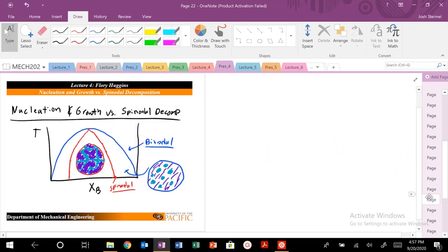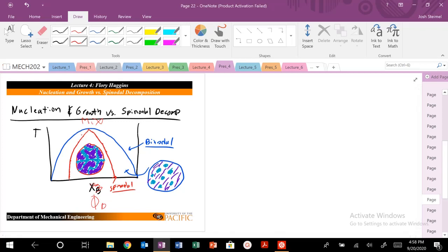One of the things you will see today is a phase diagram — XB or XA equivalent to φB — where there are two lines. Above high temperature we're in our mixed state, and below we're in a demixed state for both curves. You'll see a curve called the binodal and a curve called the spinodal. We're going to see how they correlate and how we find these points for a given temperature or chi.